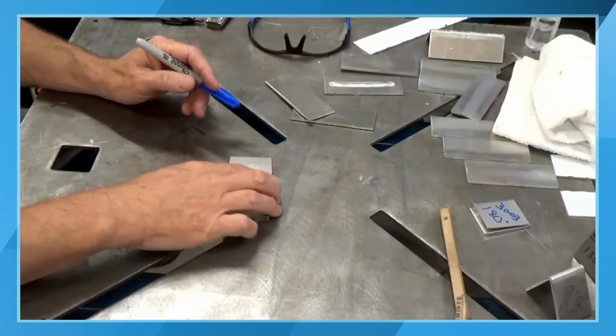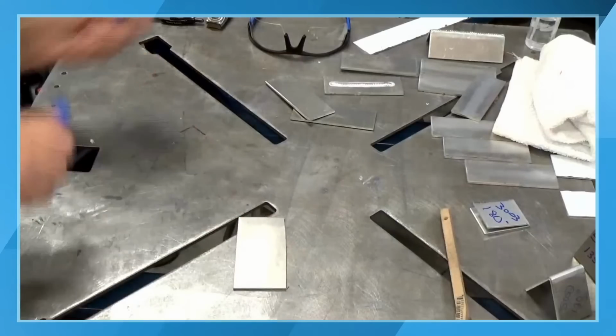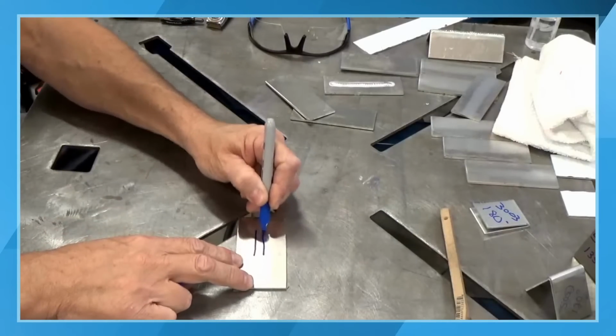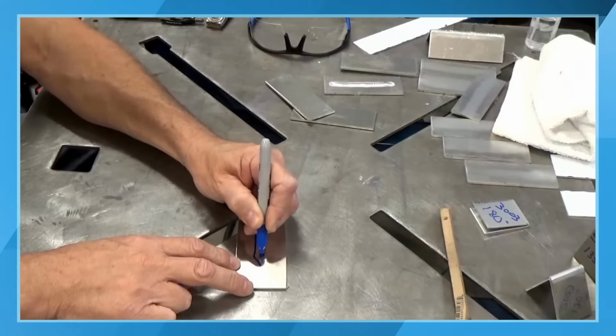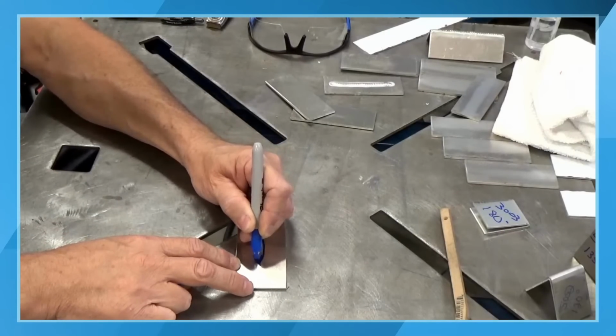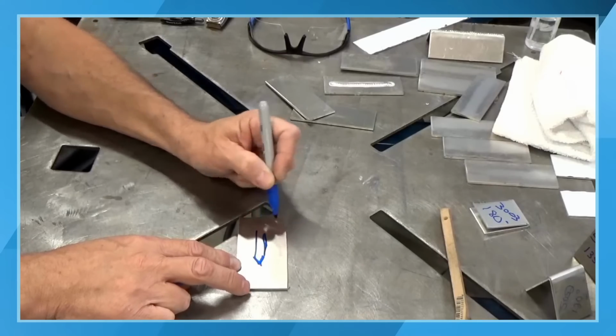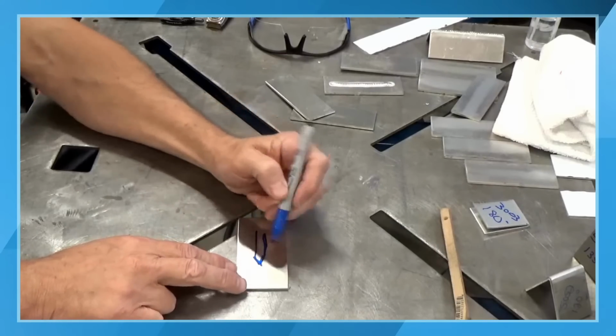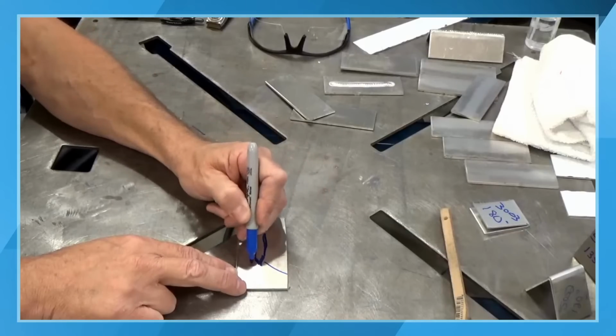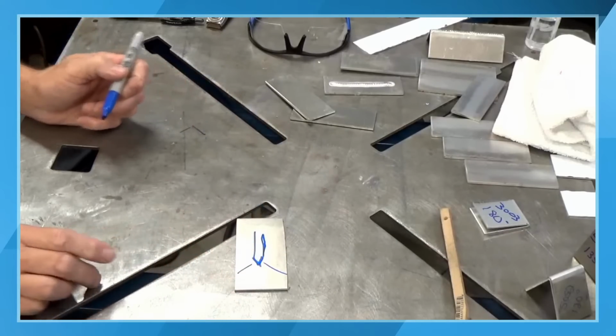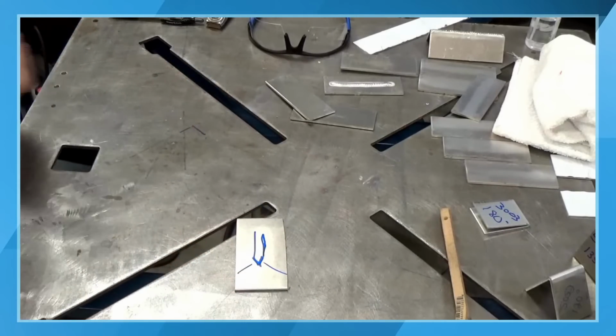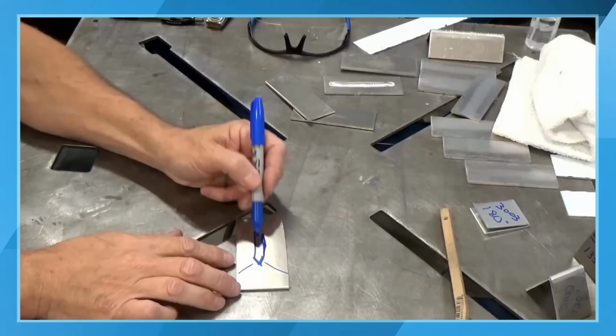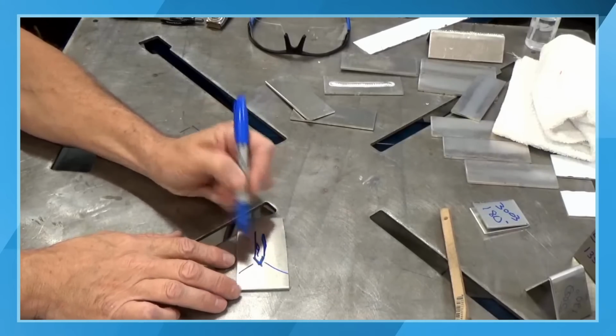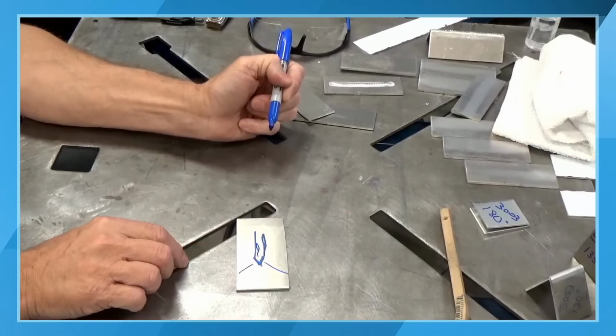So if this is my tungsten, your grind angle, and they probably talked about this on one of the beginner ones too, your grind angle is going to determine how the arc flares off the tip of the tungsten. So a lot of people think that if I put a long taper on my tungsten, it's going to be more pinpointed, and that's not correct.